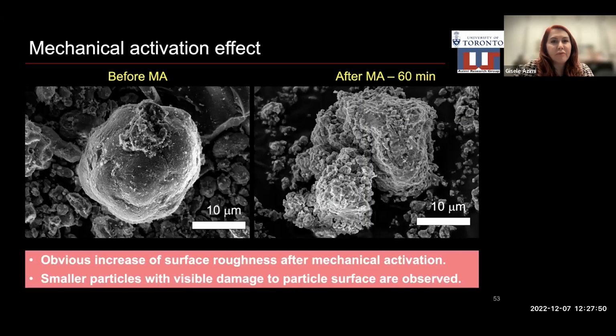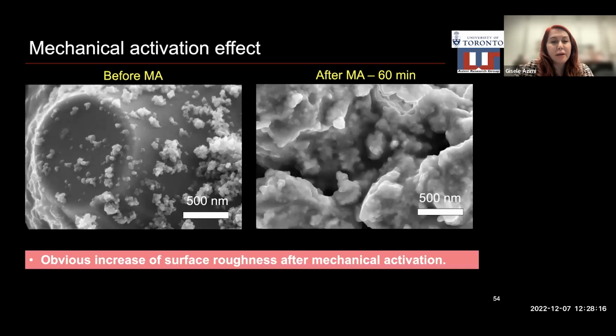We looked at the effect of mechanical activation on particles. Here you can see SEM, or scanning electron microscopy, images of the particles before mechanical activation and after mechanical activation for 60 minutes. We see an obvious increase in surface roughness after mechanical activation. We also observe smaller particles with visible damage to the particle surface. We have higher magnification images. Here the scale bar is 500 nanometers. We also observe an obvious increase in surface roughness after mechanical activation.